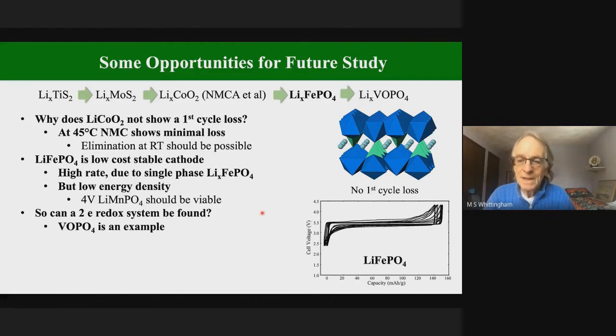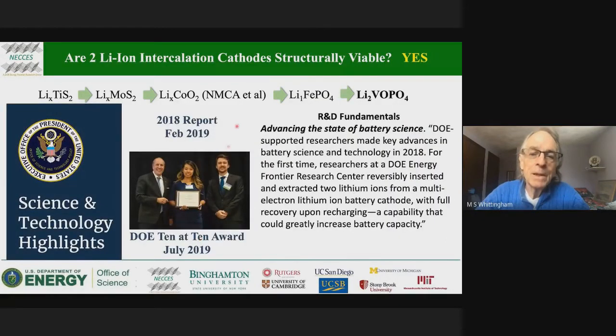Our interest, as I mentioned earlier, is can we put 2 lithium ions into this material? And we chose vanadium as a compound to do it with, because obviously you can put 2 lithium ions in. You need 3 oxidation states, then we can go from vanadium 5 to vanadium 4, then vanadium 3. And clearly this was successful, or I wouldn't be talking about it. And this was one of the 2 items that the US government highlighted in the 2018 federal report that came out in February of 2019.